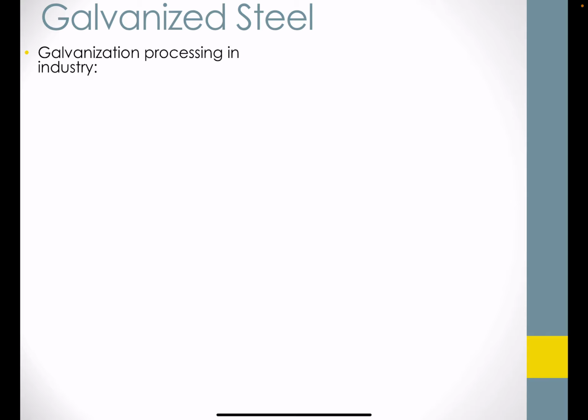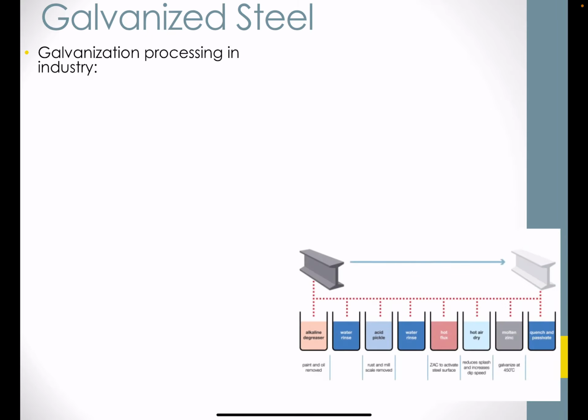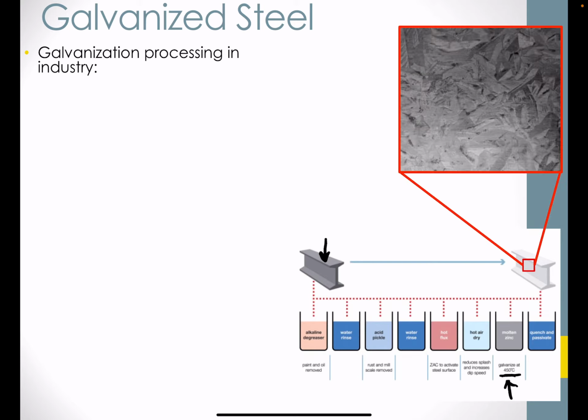Okay, a second galvanization process here is the hot melt process or hot dip method. So here what is done is typically a metal structure, steel for example, is first primed with various steps for an application of molten zinc to its surface. Notice that this is molten, very high temperature here, about 450 degrees C, to render zinc into its liquid form. And the steps ahead of that prime the surface for various chemical steps.